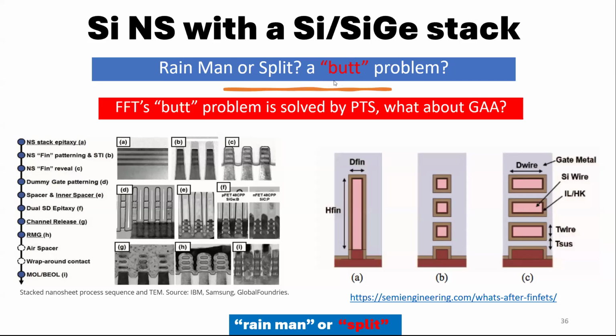There's a special butt problem. It not only happens in nanosheet, but also in FinFET. Like this fin, there's a conduction path beneath this fin, right? I call it the butt problem. And this problem is more severe in a nanosheet because here it's wider, right? The fin has a very small area here. So the butt problem, the conduction path, is much less than if you have a wide nanosheet under it.